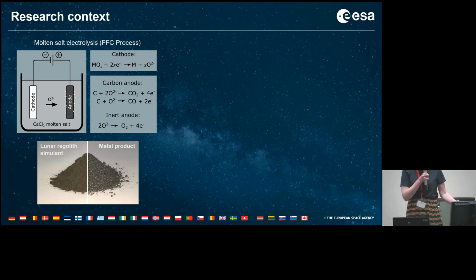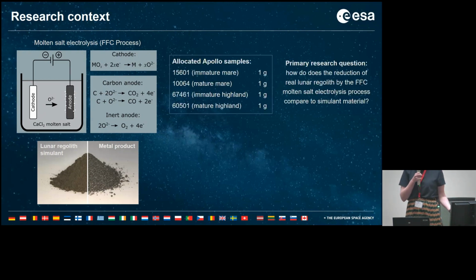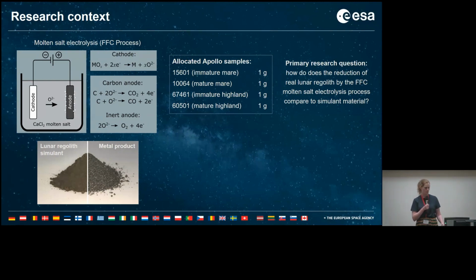But of course, it's of great interest how this process would react to real lunar regolith. So we applied for 4 Apollo samples, and we were lucky enough to be allocated 1 gram of each. We've got 2 immature, 2 mature, 2 Mare, and 2 Highland samples. The primary research question is, how does the reduction of real lunar regolith using the FFC molten salt process compare to the simulant behavior?